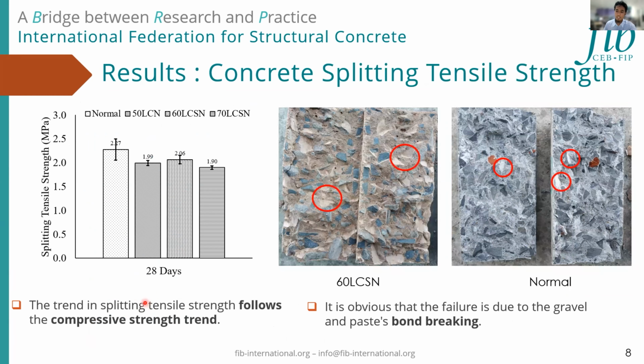And then the splitting tensile strength of the LCSN variation follows the same trend as the compressive strength. The splitting tensile strength of the LCSN variant was decreased. This image also shows that the failure was caused by a loose bond between the cement matrix and the aggregate.